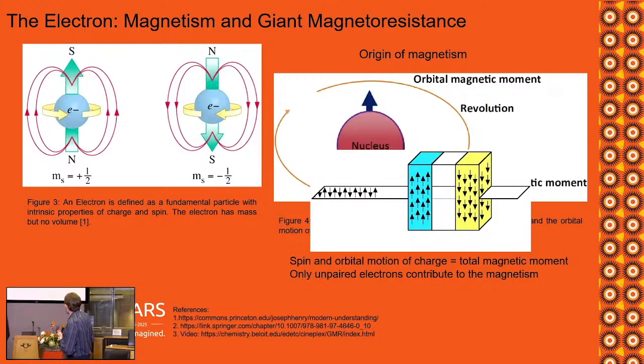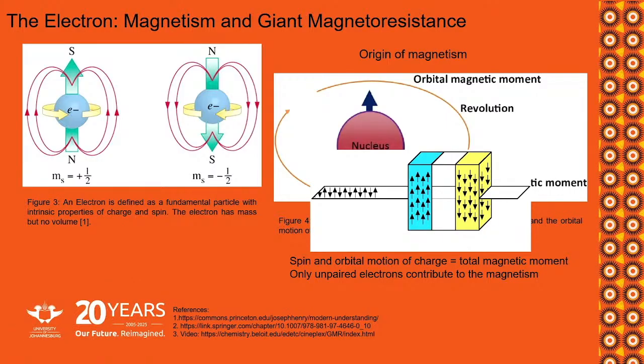So if I quickly just look here, we'll show a little video just to show you GMR. What you have here is effectively current coming in from the side. Now, a current itself has both spin up and spin down electrons, spin up and spin down channels. So electrons flow in, a current under an electric field. It sees this first iron layer. So the spin down in this case gets cancelled out or blocked. So if you look at this, that first layer filters your current effectively in GMR.